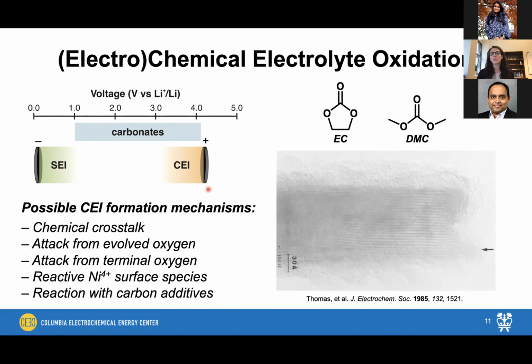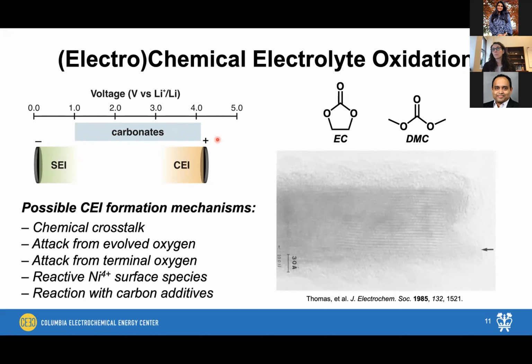So you can see that whenever we're cycling this battery to 4.2 volts, we wouldn't necessarily expect carbonate breakdown just based on thermodynamics. So if we're thinking about where this interface is coming from, one possible route might be from chemical crosstalk. So these carbonate molecules are well known to be reduced on the anode side of the battery. If there's any soluble species that are formed, they could migrate across the separator and be deposited on the cathode side of the battery, building up an interface on the positive side.